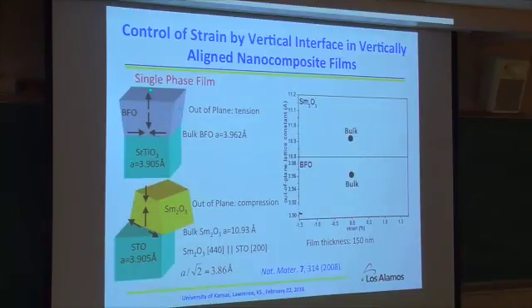For example, just a cartoon, look at this. The single phase film, if you got a bismuth ferrite here, and this is strontium titanate. If you look at the crystal lattice parameter, the thin film, that's what you expect, okay? So basically, in the plane, you have a compressive strain, and then out of plane, you just expand. For the metal oxide, it's another phase. If you put it on strontium titanate, you think about the 45-degree rotation, and that's what you expect, okay? That's exactly what you see if you do a single phase film. That's just a pure film case. Experimentally, for these two phases you will see this.